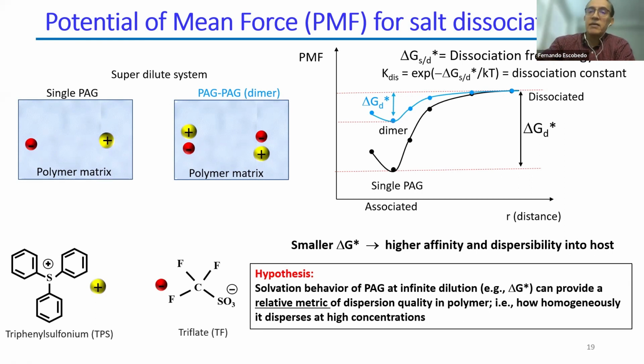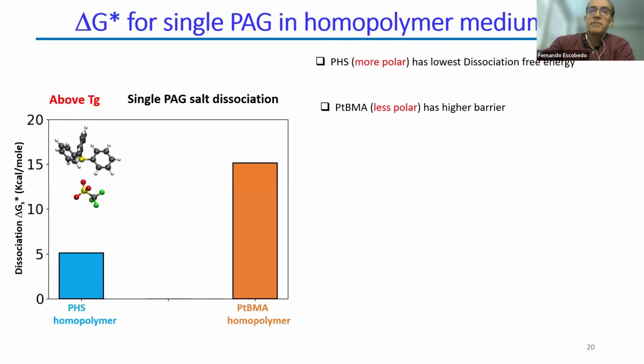But this will be the main metric to quantify and predict that solution behavior. So this shows some results for just the barriers for these delta G stars, for the case of a single path, so I'm just looking at the dissociation of anion and cation. And what you can see is that if you were to use just the pure homopolymers, PHS has a much smaller barrier compared to PTBMA. In some ways, it is expected because PHS is more polar than PTBMA.